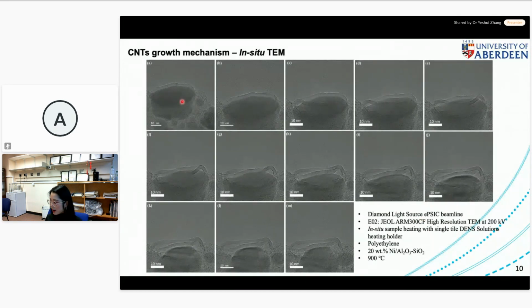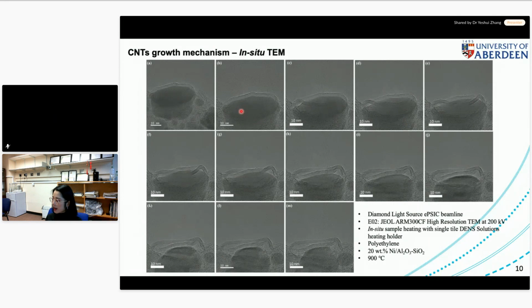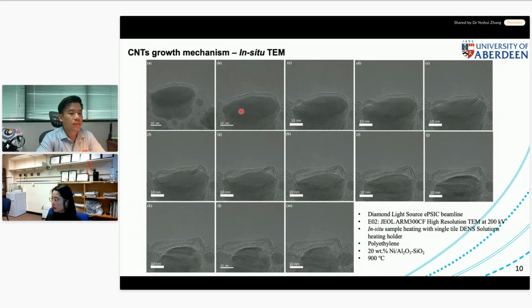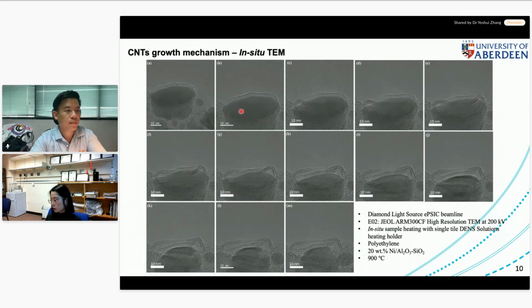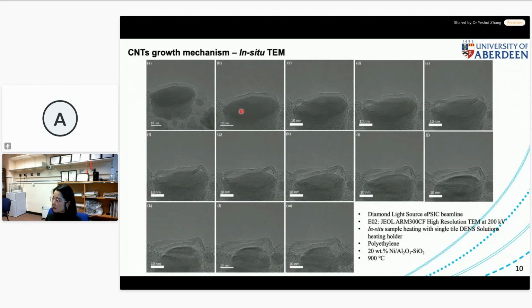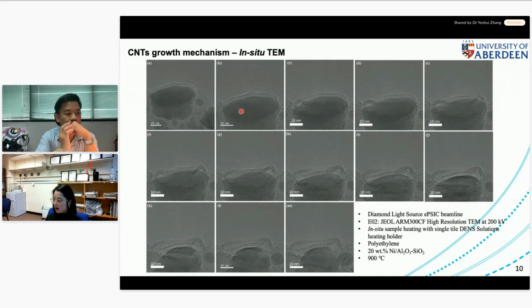And what we captured, everything happened within a minute, even less. What we try to simulate, not really simulate, is this: we mount the catalyst powders and the plastic powders in the capillary tube, and we have the heating stage. Meanwhile, we use the fast capturing function of this in situ TEM to capture this particle.